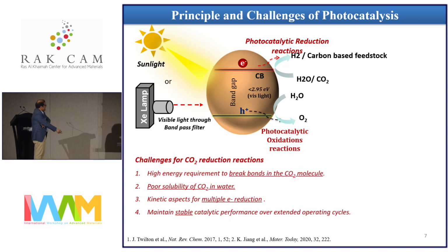So these are some of the challenges of CO2 reduction reaction. There's a high energy requirement to break the CO2 molecule — the C-O bond energy is 750 kilojoules per mole. Secondly, there's the poor solubility of CO2 in aqueous medium. And as I told you, there's an 8-proton reduction for CH4 formation, so the kinetic aspect is also very important. And you have to maintain stable catalytic performance over an extended period — your catalyst has to be very stable.